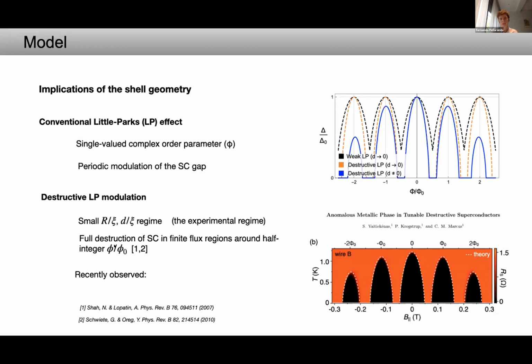In those cases, the superconducting currents circulating around the shell induce an additional pair-breaking mechanism that leads to the full destruction of superconductivity in finite flux regions around half-integer fluxes. This was recently observed in this experimental work, also by S. Vaitiekenas et al., in which at zero temperature, we clearly see how metallic and superconducting phases oscillate with the applied in-plane field.